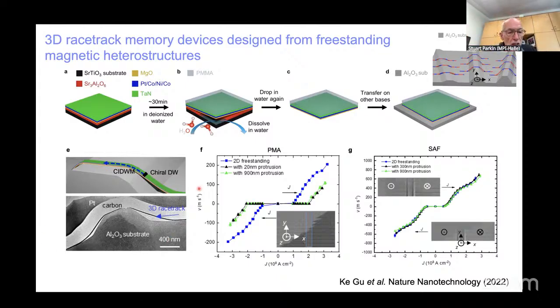And as shown in the bottom left, this is a cross-section transmission electron micrograph of this membrane, the 3D racetrack. And in cross-section, you can just see it looks like this black line, which follows very closely the underlying sapphire substrate. And so we've demonstrated the possibility then of building essentially a three-dimensional racetrack. And in this racetrack, then, we demonstrated, on the right-hand side, this SAF is a synthetic anti-ferromagnetic racetrack.